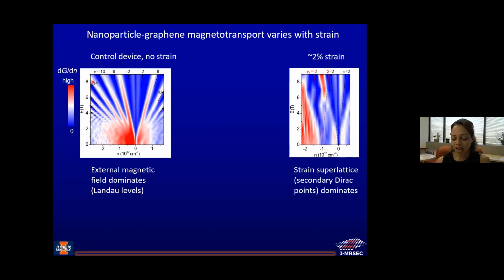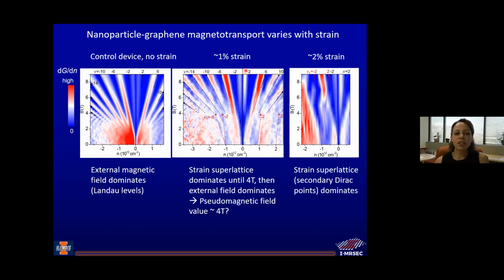Now it's interesting, what hadn't been seen before is for weaker strain, we see some in-between behavior where we have what looks like a strained superlattice dominating at low magnetic fields, and then a standard Landau fan diagram coming into play at higher magnetic fields. So what we believe is happening here is an interplay between a pseudo-magnetic field dominating for the low fields and then the external magnetic field dominating for the high fields.